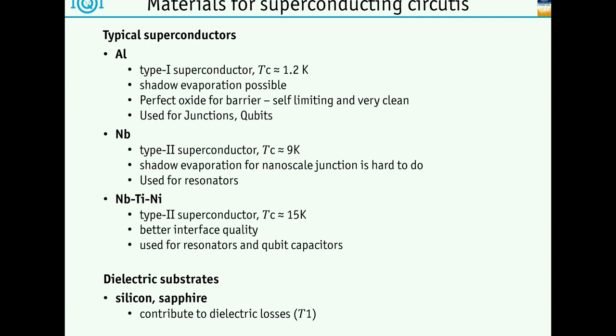It's not so ideal for junctions because it's much harder to actually do shadow evaporation with it. Typically, one can only etch niobium very well. A new material which has come up in the last couple of years is, well, it's not a new material, but a material that hasn't been used so far up until very recently, is niobium titanium nitride. It's also a type 2 superconductor with an even higher transition temperature.